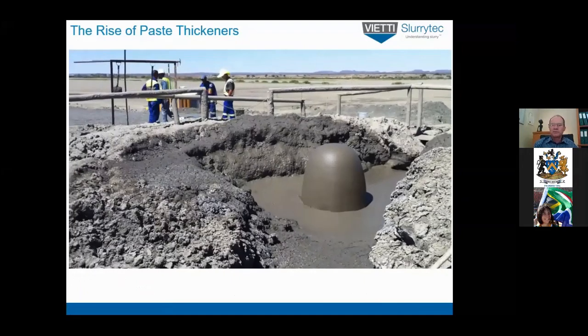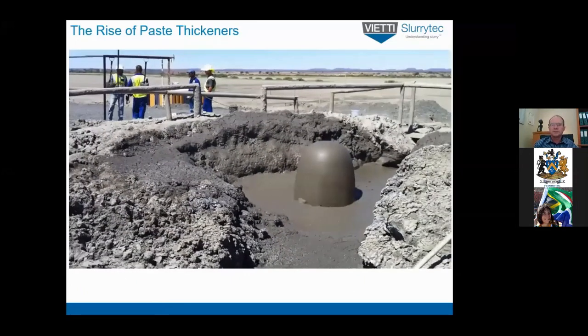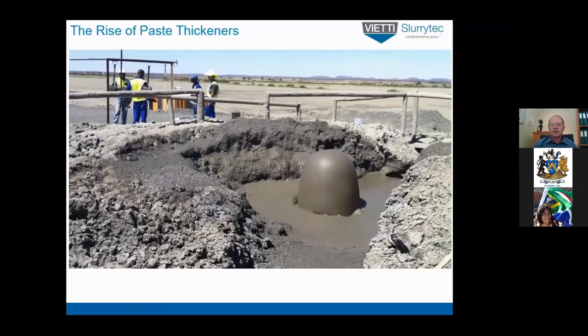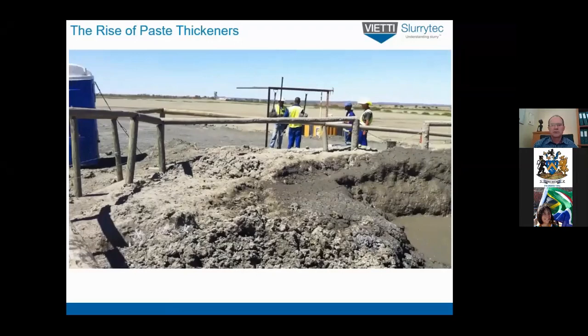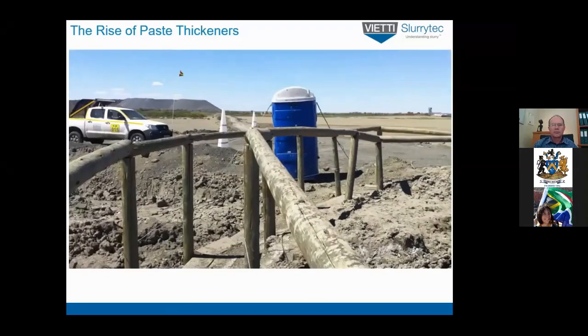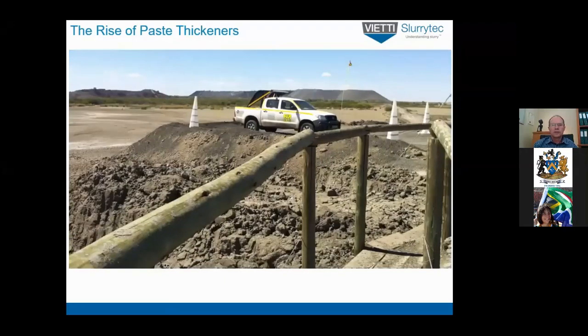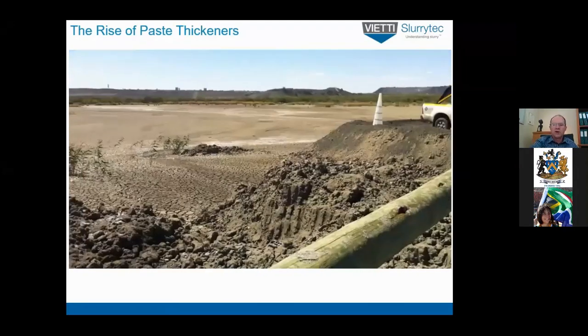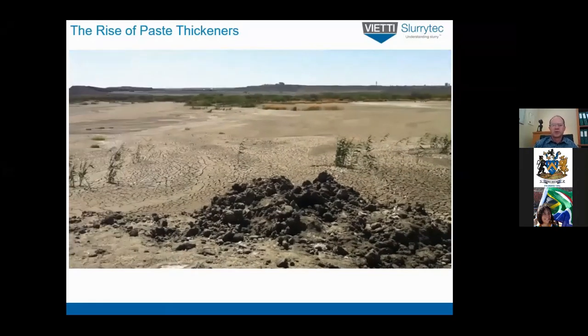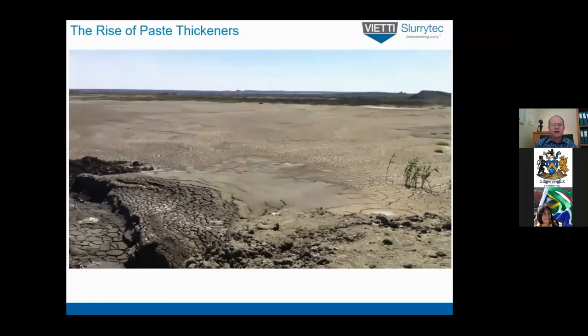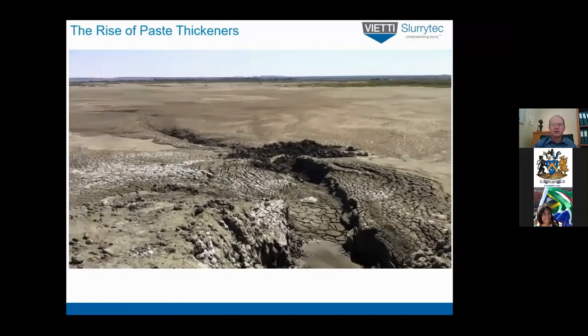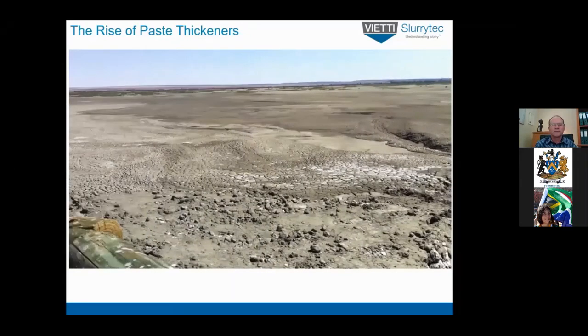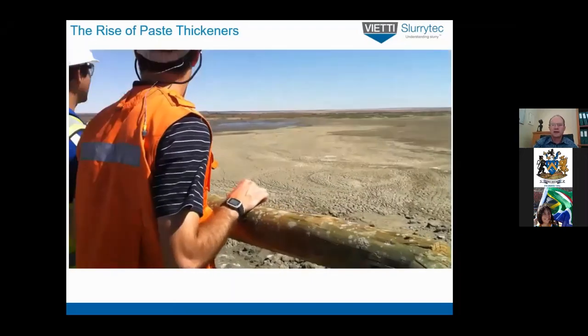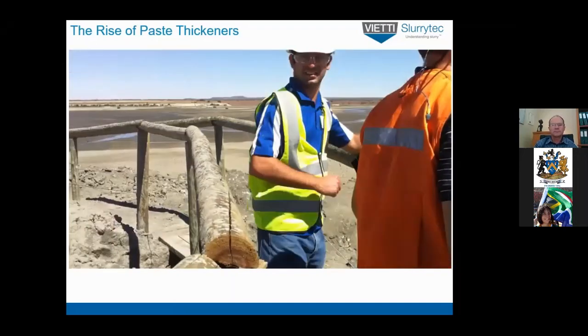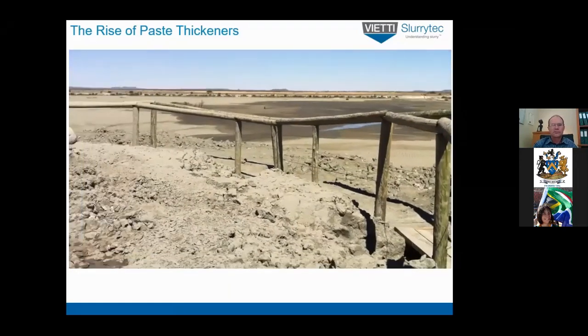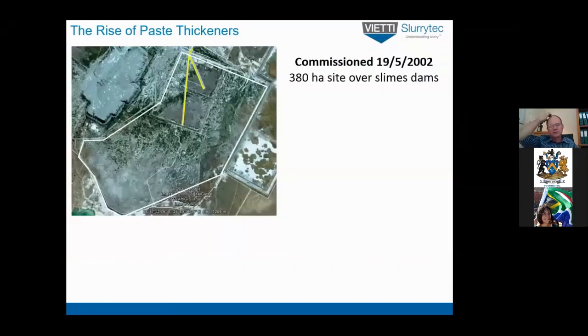So that's the end of the pipe running into the plunge pool. And you can see there's no water. This dam is dry. And there were obviously flows in this direction at some stage. It's a bit noisy because of the wind. This is where they were flowing out at one, and then they let it dry. And there you can see the tailings tunnel, where the new material is coming out. Okay, so yeah, that gives you an idea of how it worked.